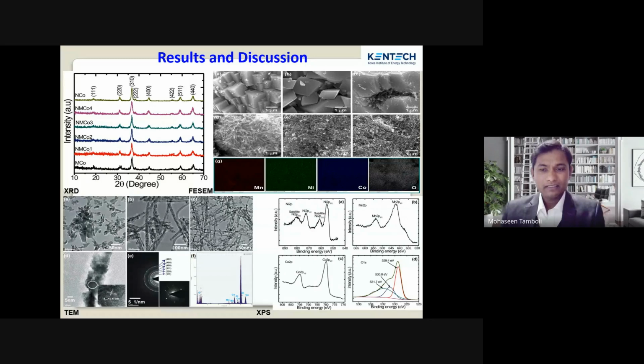This XRD pattern of all the samples with the different compositions, when we check the JCPDS data, matches very well with the MnCo2O4 spinel structure. Then we studied the surface morphology of our material. In FESEM, you can see figure A is showing the pure MnCo2O4. As I mentioned earlier, pure MnCo2O4 shows cube-like structures.